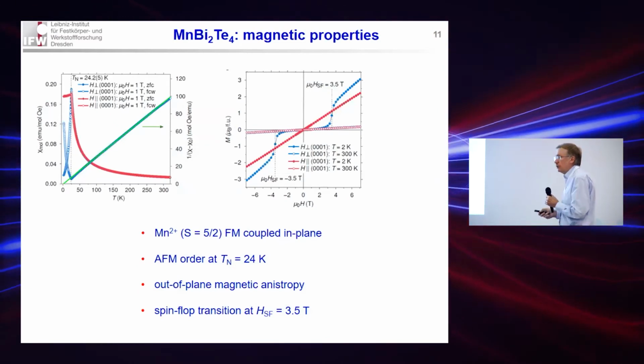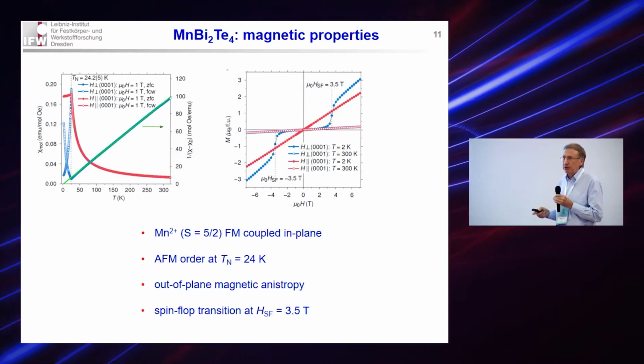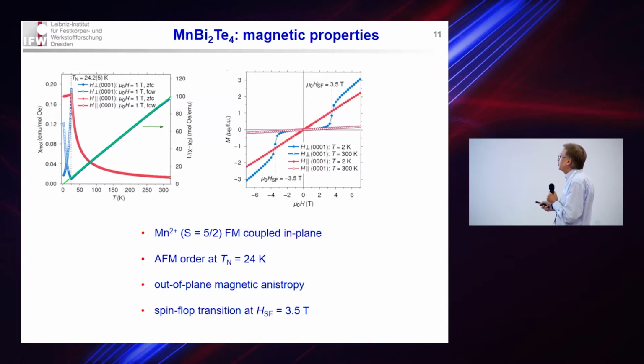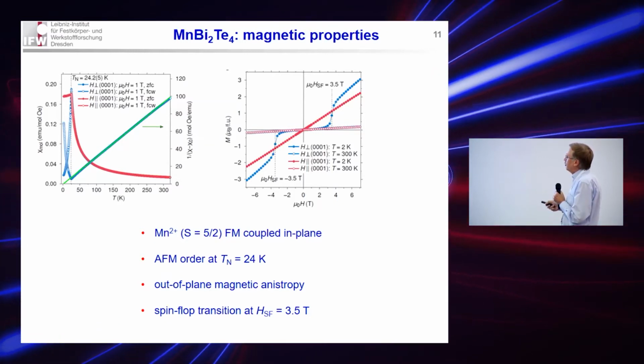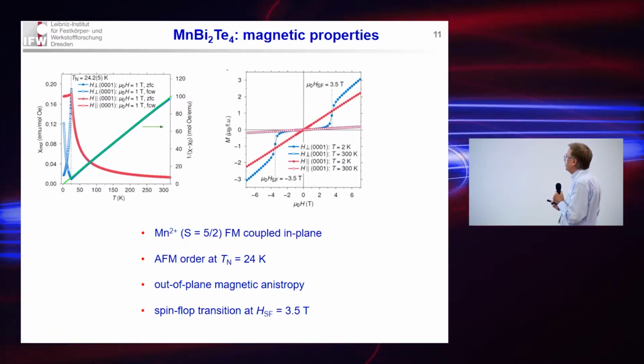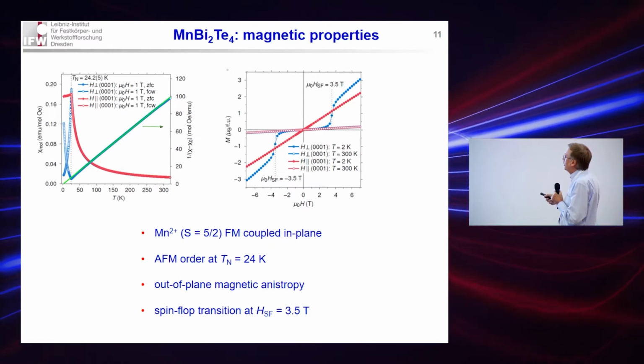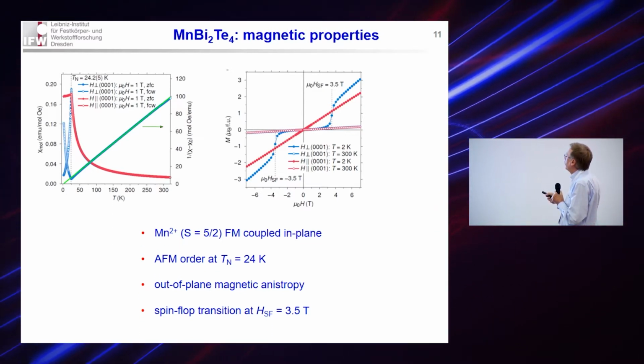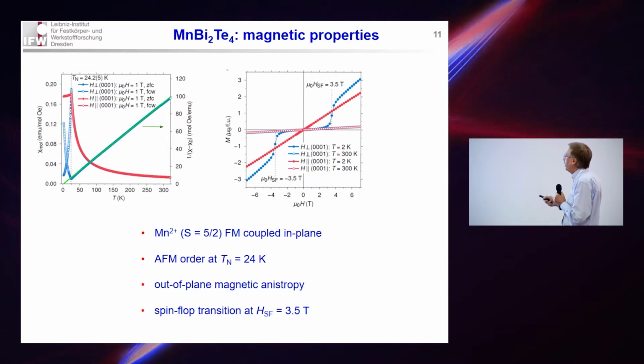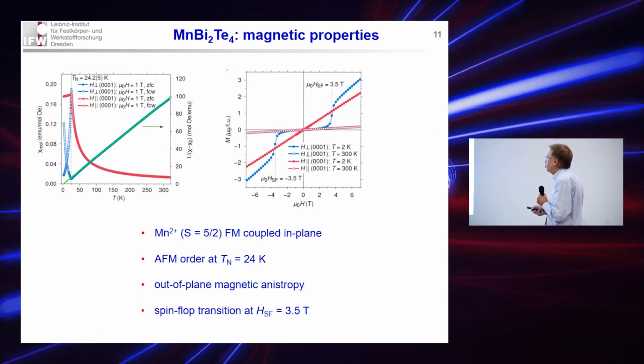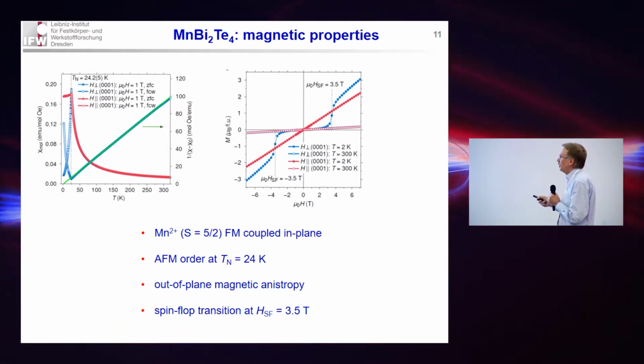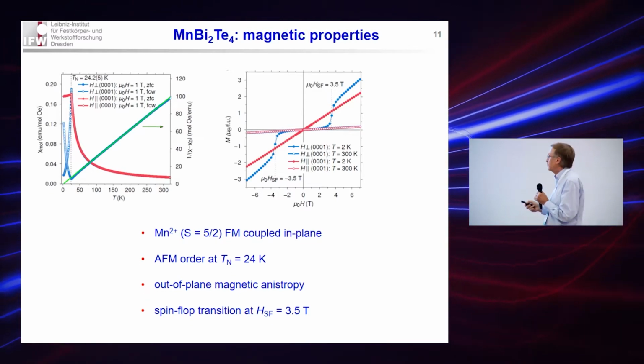Now, if one looks at the static magnetic properties of this compound, they're quite usual, nothing special. One measures the temperature dependence of the magnetic susceptibility and observes a peak at a temperature of 24 Kelvin. This is for the 1-2-4 compound. And the susceptibility drops down at low temperatures, indicating an antiferromagnetic phase transition.